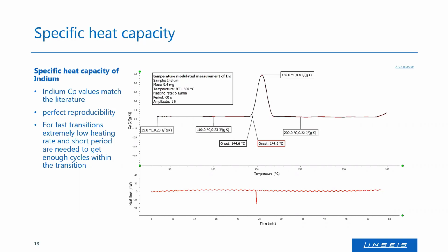So what we also can see, of course, is the melting at normally 156.6 degrees Celsius. And as I already mentioned, the CP isn't defined in this transition, because the measurement system has to bring more heat into the sample to follow the temperature profile. And for this reason, it looks like there's a bigger CP, a bigger heat capacity for the measurement system, but of course it's just the endothermic effect of the melting here. So for this reason, we cannot define the CP during the melt. But what we can look at is behind this melt. We will see the value for the CP there is a bit lower, but this is also possible for materials. The CP of a liquid is lower than the solid before melting.